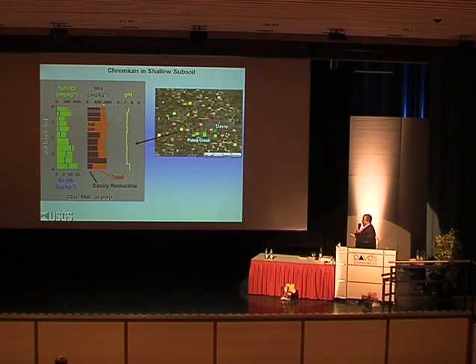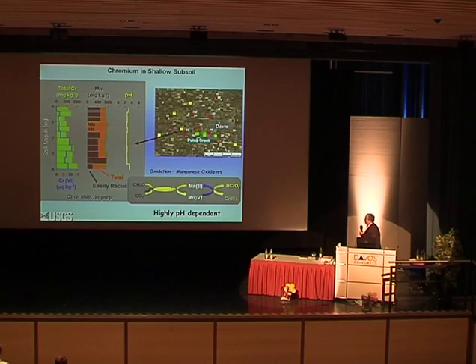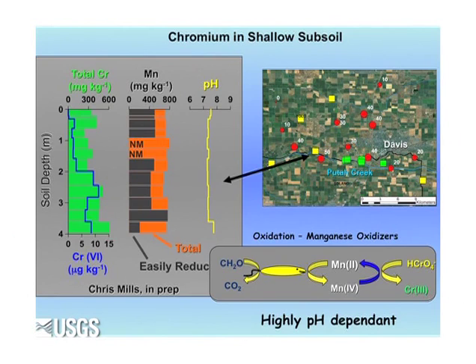On the right is a plot of total manganese in orange and easily reducible or reactive manganese in this darker color. The reason manganese is important is that the primary oxidant from insoluble chromium 3 to toxic chromium 6 is manganese oxide, which couples to the chromium 3 and produces manganese 2 and chromium 6. Microbes are involved in reoxidizing the manganese. They do that at a rate many orders of magnitude higher than would occur naturally.